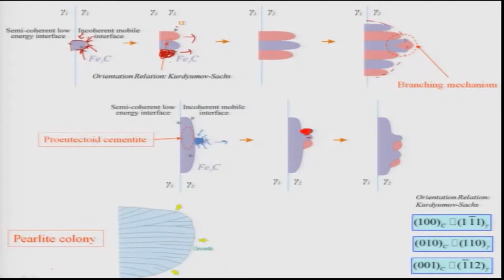So nucleation of these phases can happen in many ways. Similarly, for hypo-eutectoid alloys, you will have alpha on the grain boundaries, like if I have two grains, gamma 1 and gamma 2, and then you have alpha presence, which is pro-eutectoid alpha. This alpha will allow the nucleation of the alpha phase of the pearlite very easily, because it is heterogeneous nucleation on the same phase. So energetically this is very favorable.